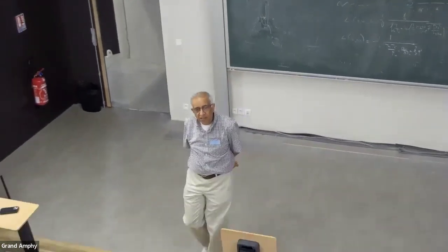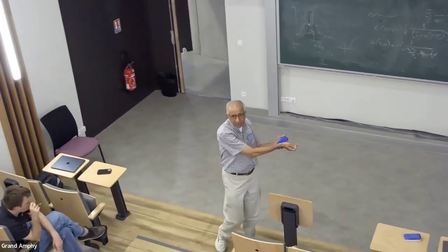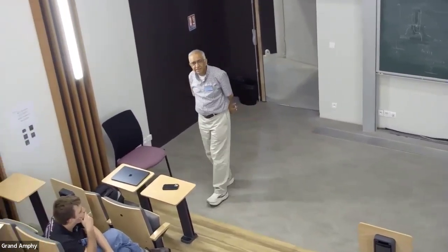Spectral weight to add a particle on the positive bias side, spectral weight to take out a particle on the negative bias. I may have got the sign wrong, but you know what I'm talking about, because the negative sign of the electron always confuses you. So gap here is in the sense of tunneling probability. It's how much spectral weight you have to tunnel in. That is the measurable quantity. Maybe talking about it as a gap actually is hurtful, but it is what it is.